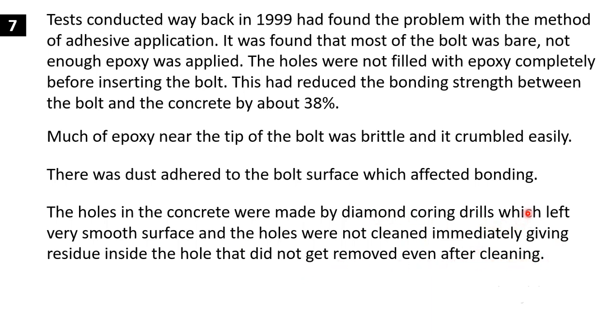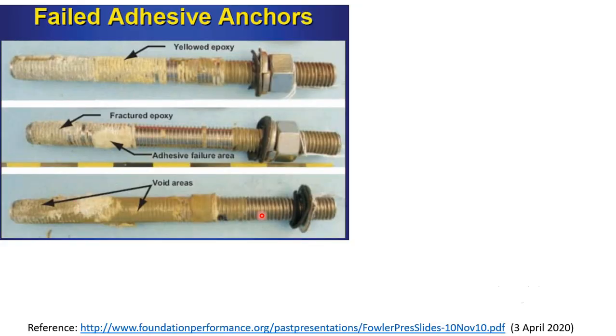So another problem was that diamond coring drills were used, which left the surface of the hole very smooth. And also the residue of the drilling process should have been removed immediately, but it was not, and therefore some of the residue got stuck inside the hole, which also affected the bonding between the bolt and the concrete. These pictures show the failed adhesive anchors.